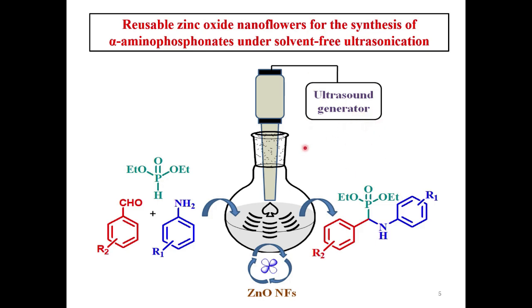At the same time, we have added zinc oxide nanoflowers as a catalyst, and we have operated this reaction with the help of this particular process. This is the complete process. Here, for the formation of the alpha aminophosphonate, there is an aldehyde group, an amine group plus a phosphonate group, and we have added these into the reaction, and they form alpha aminophosphonate.